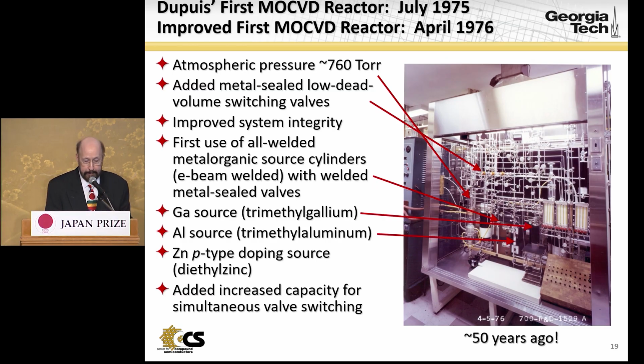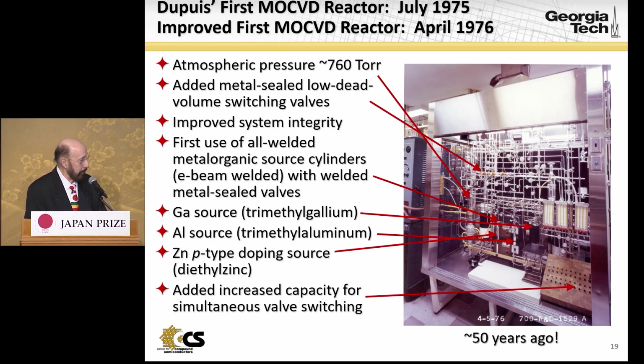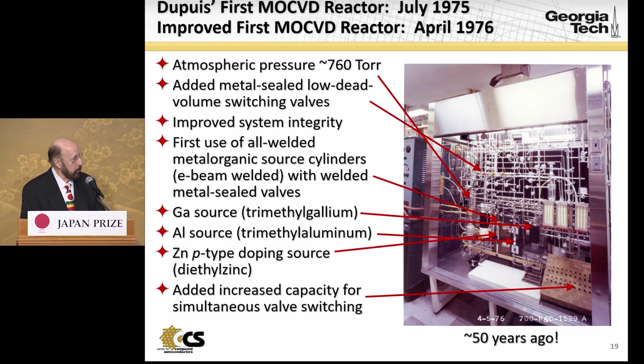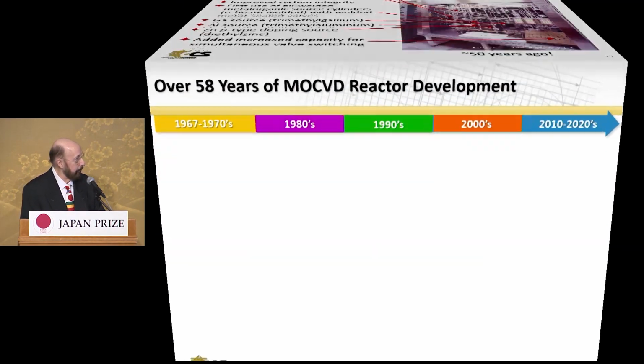Because we were limited in finances, my temperature baths were ice to control the gallium temperature and room temperature to control the aluminum temperature. We had no constant temperature baths. We also had diethyl zinc for P-type zinc doping. And I built this beautiful little box to control the valves so I could switch multiple valves at one time to create abrupt interfaces. So this was a very useful tool at that time frame, but it's now 50 years old and we have much better tools.